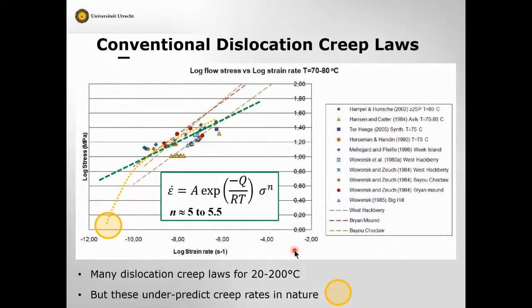All right, so how does that help us? Well, it means that we have a theoretical basis, a mechanistic basis, to fit a particular functional form to this data, which indeed is this power law form. There's a stress dependency here, but that's not important for the upper crust. It's only important for identifying the mechanism. So we can derive a mechanistic basis for this type of equation, and with an n value of around 5, you can be pretty sure that you could extrapolate this data to very low strain rates